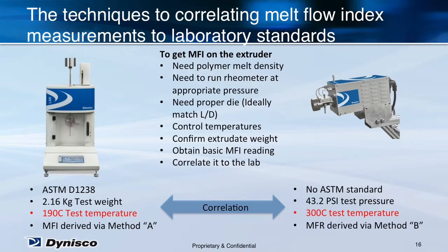In the last slide, I proposed taking extrudate from the rheometer back to the lab for testing. This is a good idea because polymers may degrade as a function of their time temperature history, so you want to understand what the MFI of the actual material checked on the machine is for comparison purposes. If there is an issue with degradation for your polymer, you can work with Dynisco to calculate the residence time of the specific machine configuration that has been proposed before finalizing the configuration.